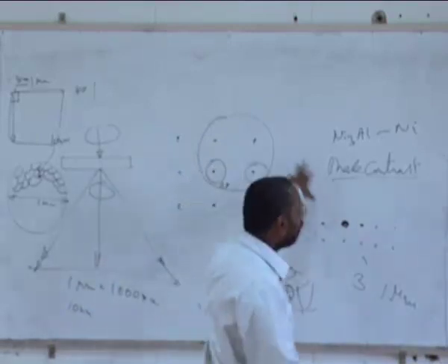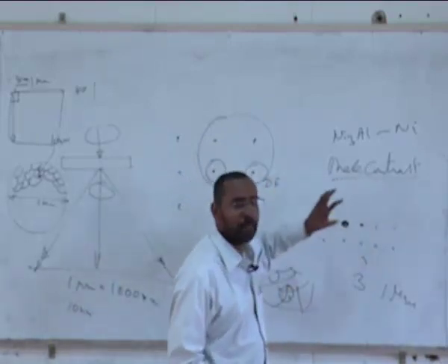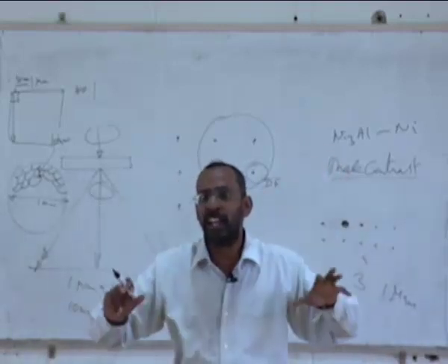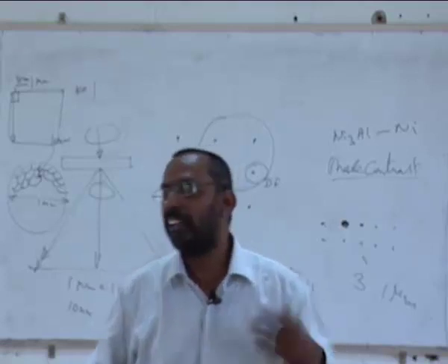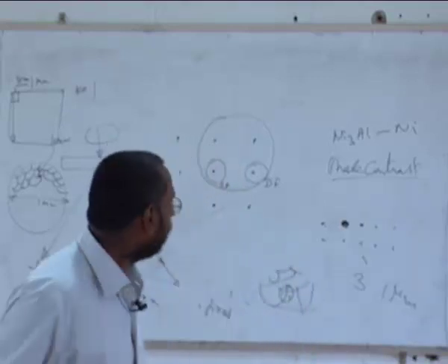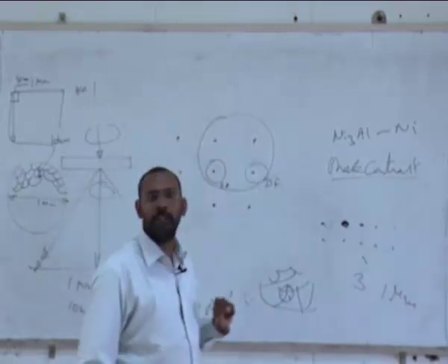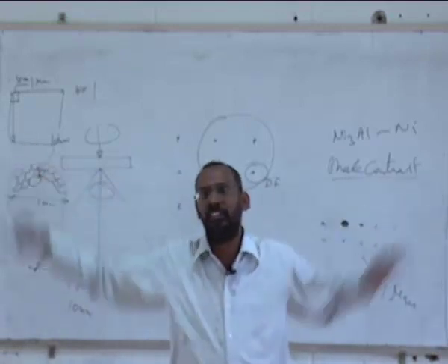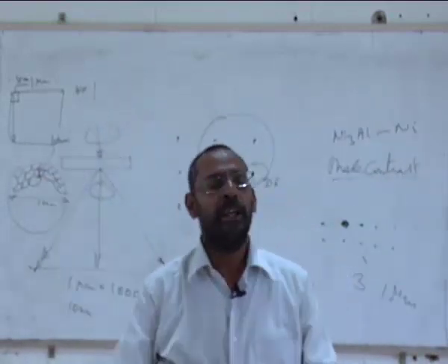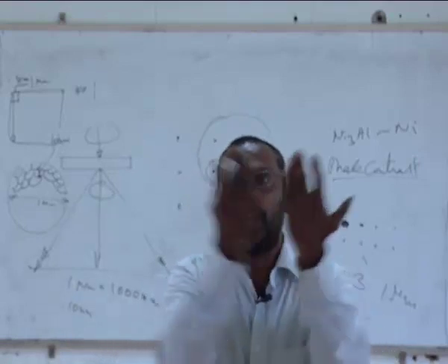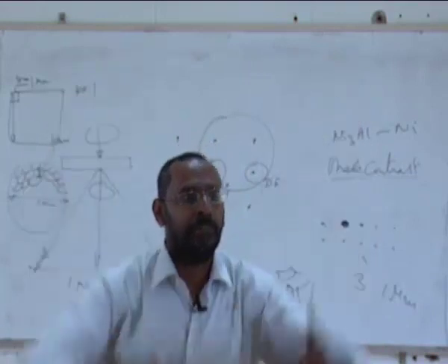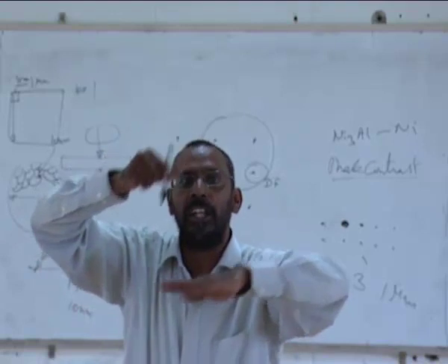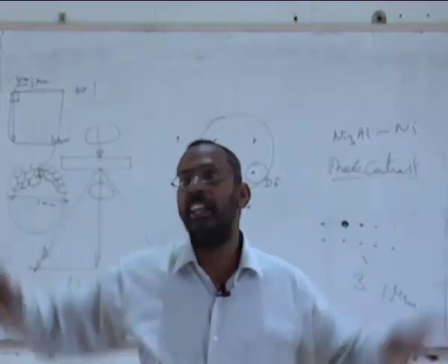So what happens is, when I get this phase contrast image, wherever the atoms are, that particular region looks brighter. Wherever the atoms are not there, that region looks darker. And that is how you get a phase contrast image. By considering both the transmitted and the diffracted beams, you will be able to see white spots periodically arranged in a 2D kind of structure. And if you can see that, that is nothing but one of the atomic planes, depending on which plane my beam is perpendicular to. That plane, how the atoms are arranged in that plane, is what I am seeing.